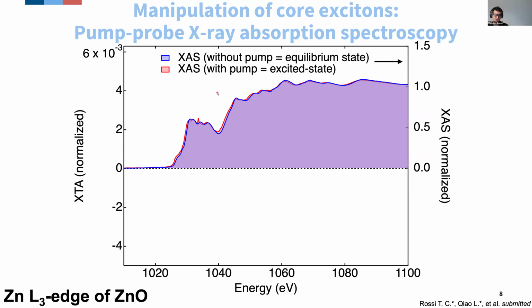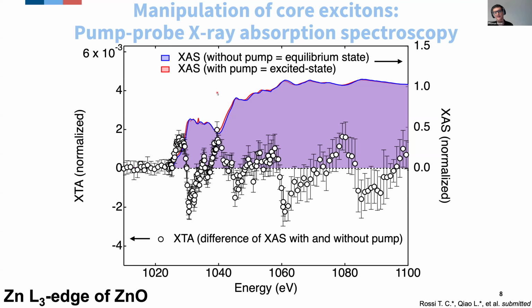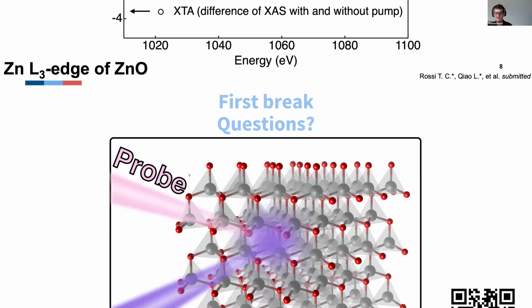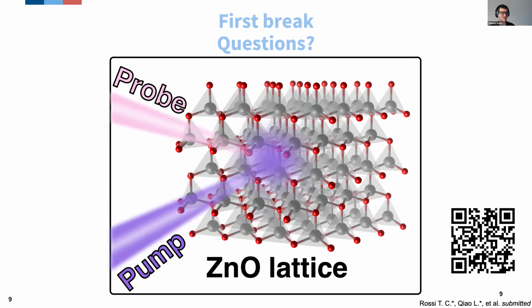And usually the differences between these two spectra are quite small. So the way we depict experimental data is by looking at experimental transients, these black circles here, that are essentially the difference between the red and the blue XAS spectra. So we prefer to highlight what the differences are when the sample is excited or unexcited by the pump laser. Positive signals mean that the sample absorbs more when it's optically excited, and negative signals mean that the sample absorbs less. And with this, it's the end of my introduction. If you have questions about the experimental setup, now would be a good time to ask.